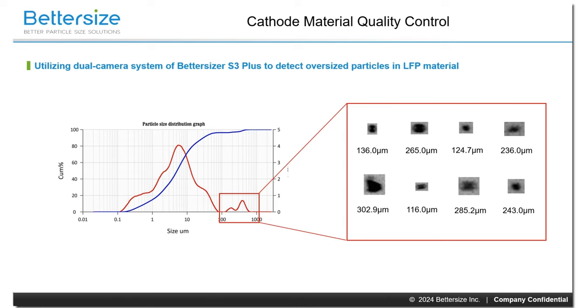Check the single particle gallery of Bettersizer S3+ measurement results. We can find they are oversized LFP particles and some agglomerations. To eliminate oversized LFP particles, improvements in grinding or other processing are required. As for agglomerates, changing dispersion settings such as using a higher power of ultrasonication can be helpful.